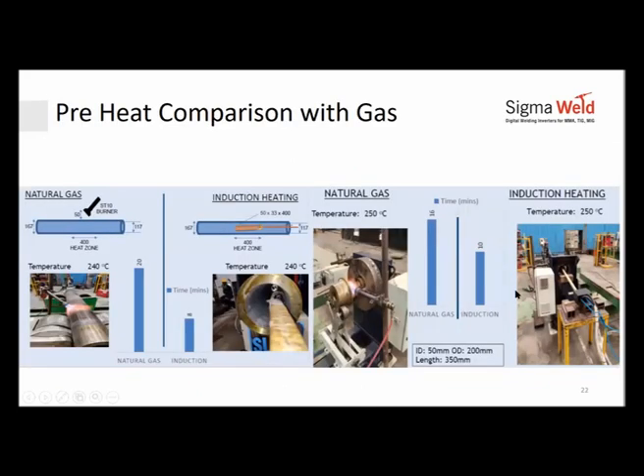Here is a comparison with a gas-based system. These were trials done for one of our customers. If you look at this pipe here, it needs to be cladded from inside. So the temperature needs to be ensured that on the inside, the temperature is correct. The temperature to be achieved was about 240 degrees. As you can see, the ID is 117, OD is 167, 50 thick. So wall thickness is about 25 mm.